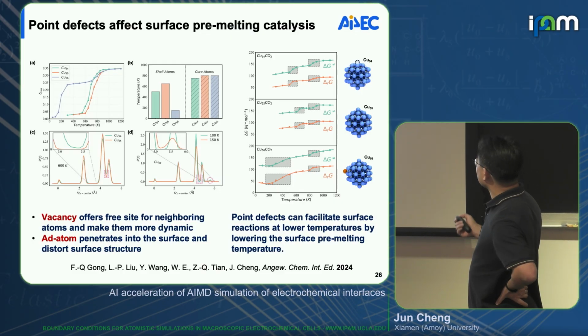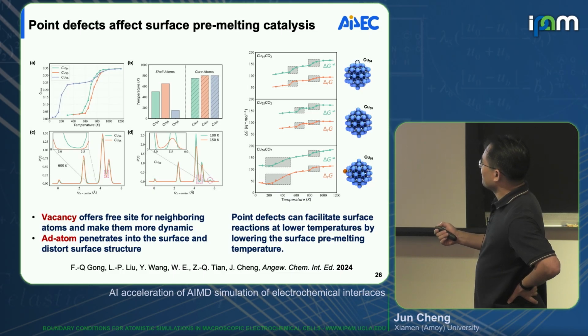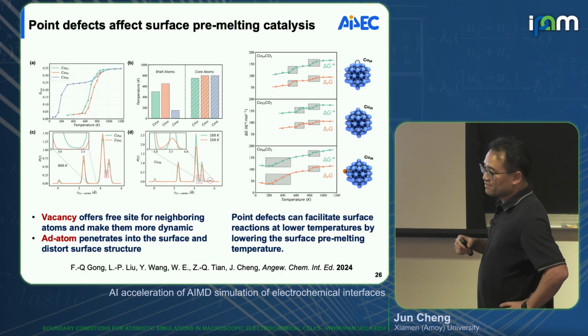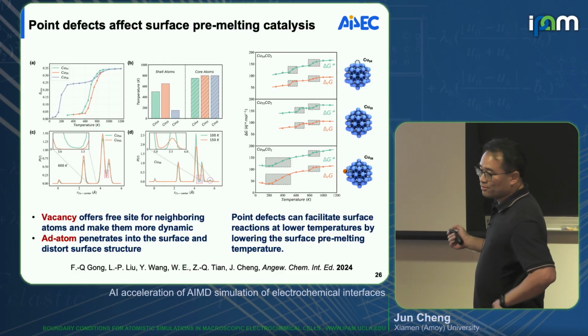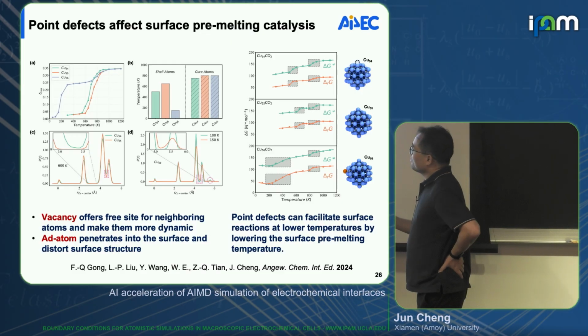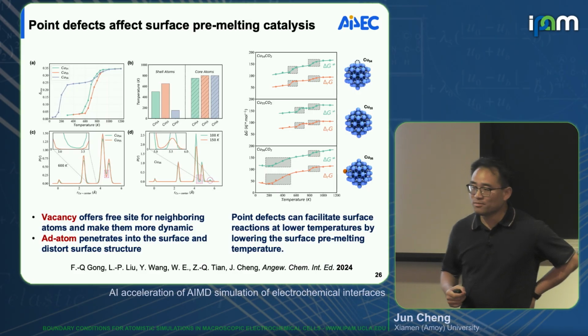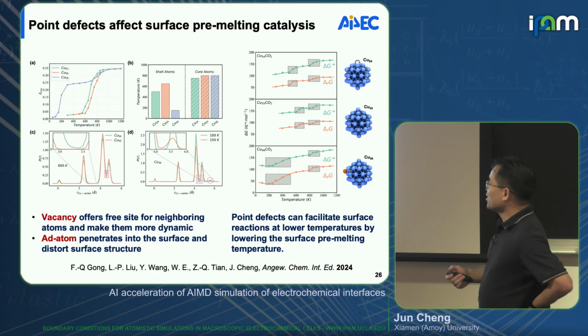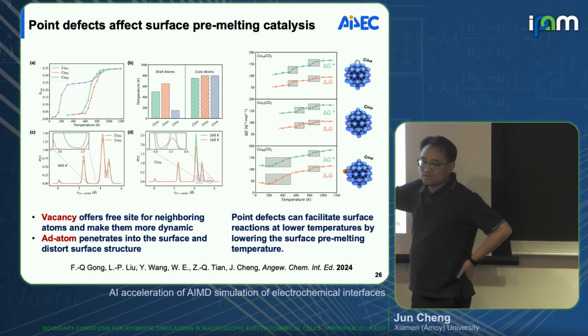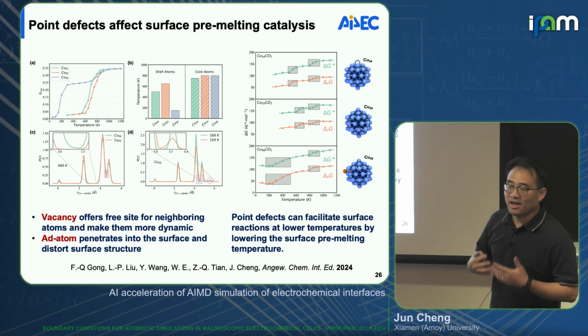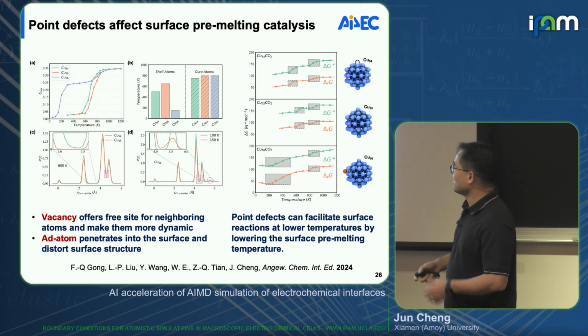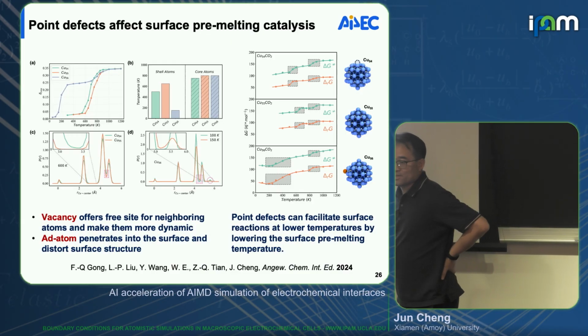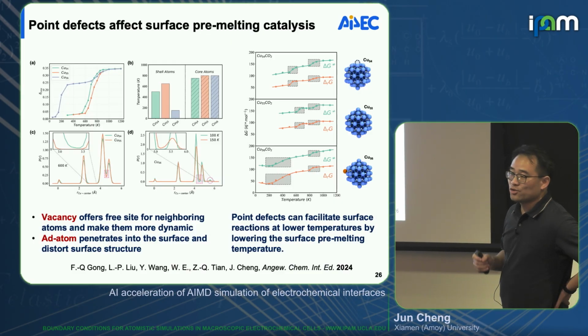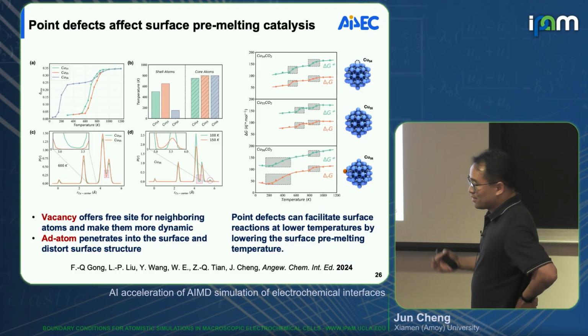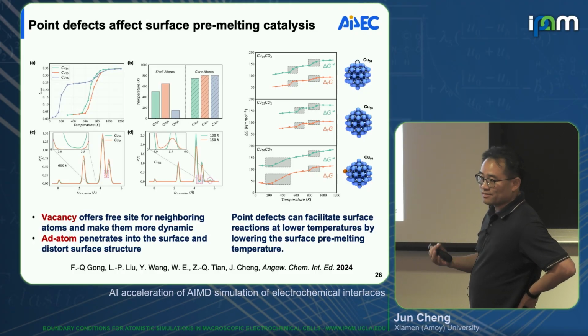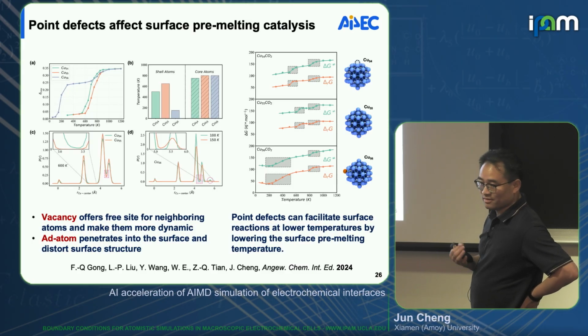And we also look at the point defects in this case, because nanoclusters tend to have many, for example, vacancies or ad-atoms. With a vacancy, we can see the surface melting temperature decrease by roughly 50 or 100 K. But to our surprise, if we have one ad-atom, this point defect can reduce the surface melting temperature by almost 200 or 300 K. That's just because this ad-atom can penetrate inside the surface, cause strain, and then make the surface more dynamic. Just to quickly show, this melting temperature is around 300 K. It's literally room temperature. So you would imagine the surface of a nanocluster catalyst is more dynamic than we would expect.